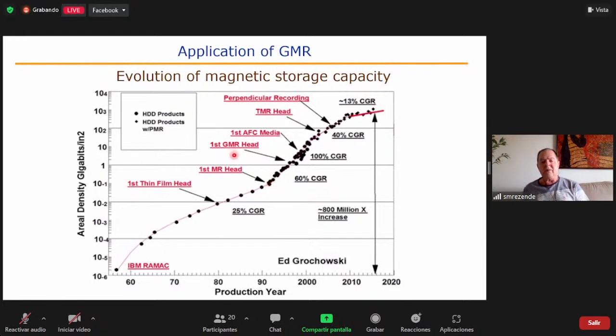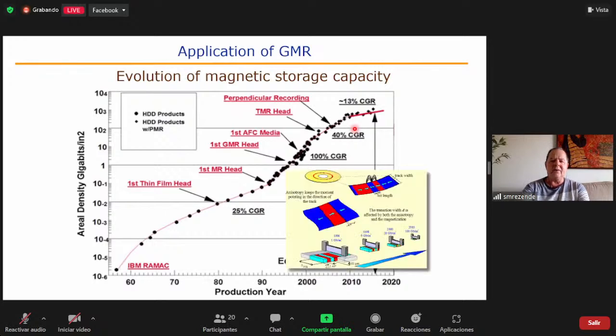The introduction of magnetoresistive head and giant magnetoresistance head changed the magnetic industry. You see, the vertical axis here is in a log scale. And as you can see, the introduction of magnetoresistance had changed the slope of the evolution along time. And this made possible hard disk drives, very large capacity, because this made possible smaller and smaller sensing heads.